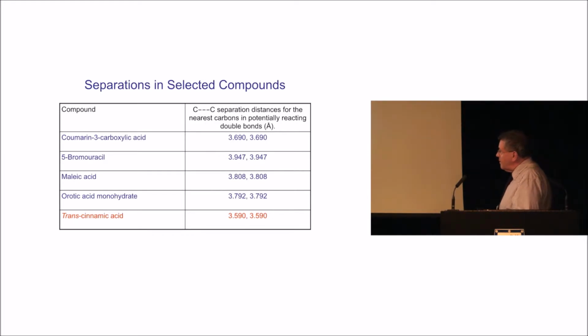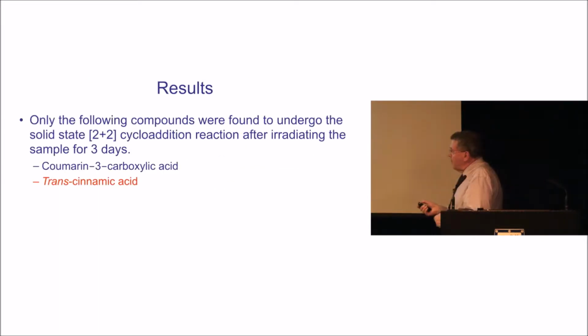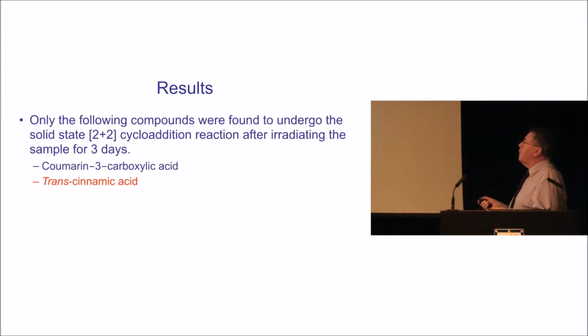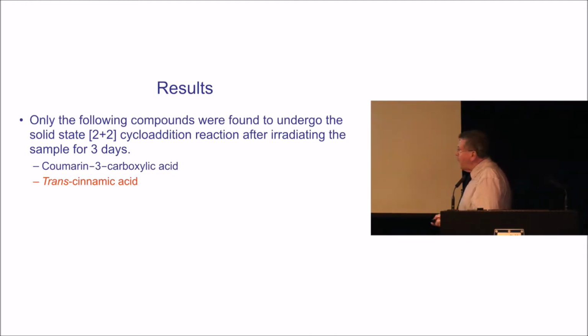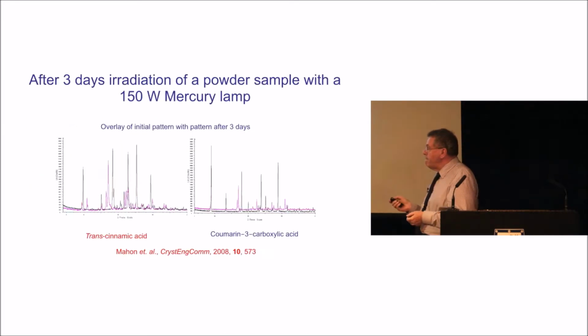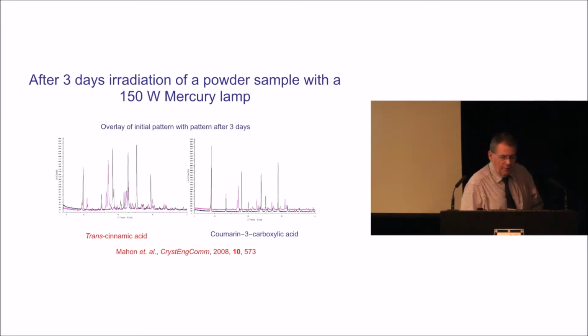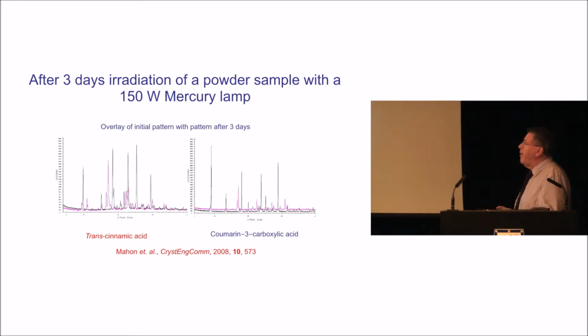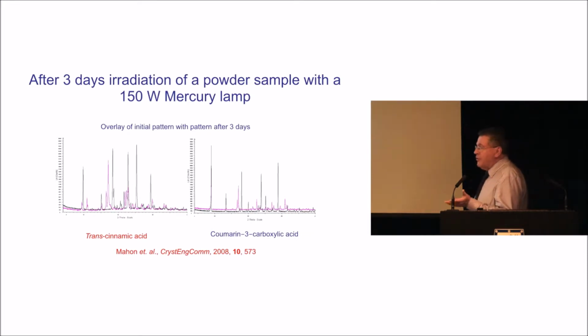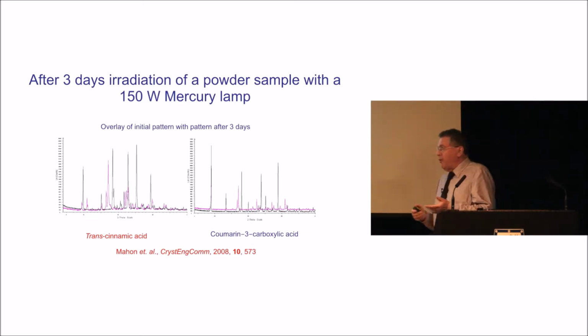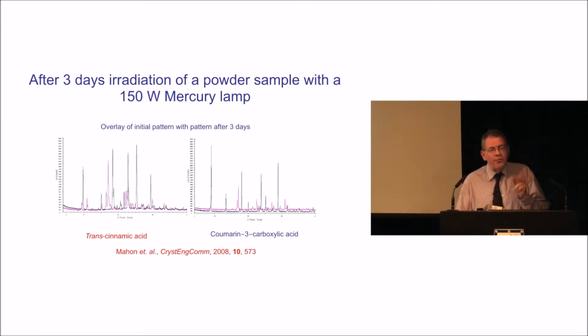We had a look at these. If you look at the carbon-carbon intermolecular distances, you can see they all obey the criteria. They're all below 4.2 angstroms. So they all ought to go. We tried 3 days light irradiation. The trans-cinnamic acid we knew should go, it went. The coumarin also went, the other 3 didn't.